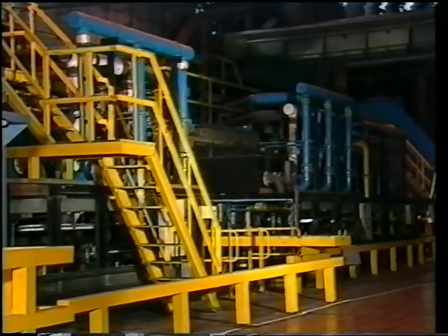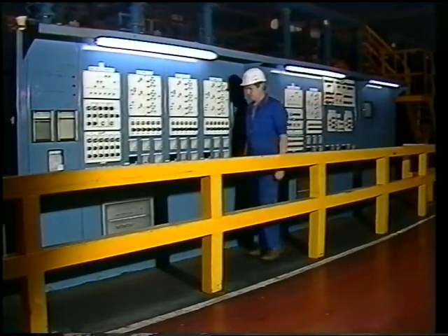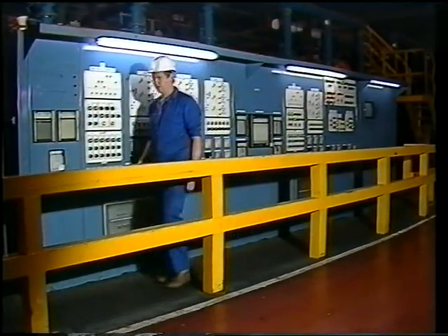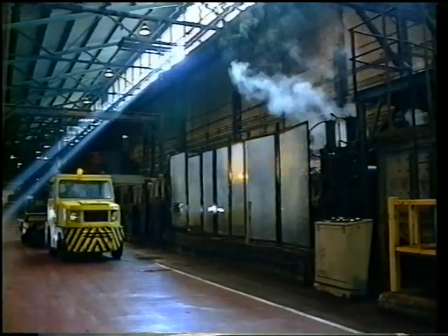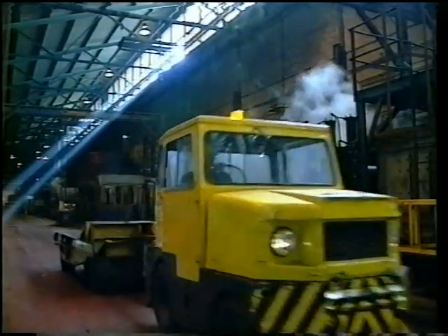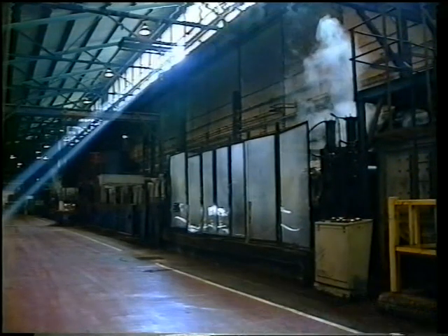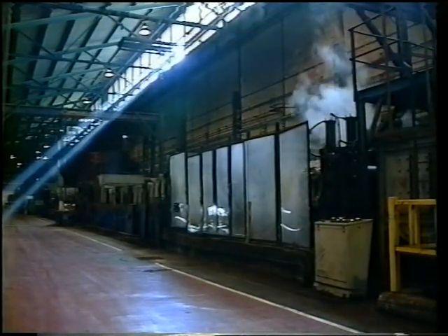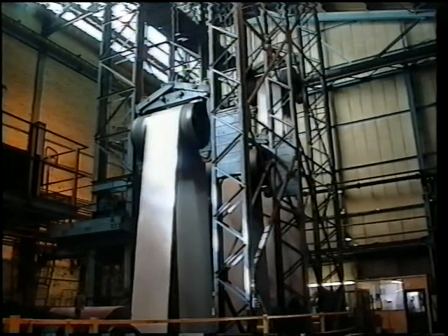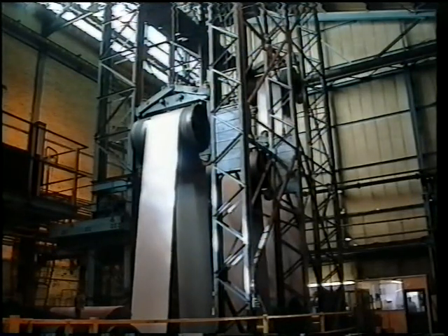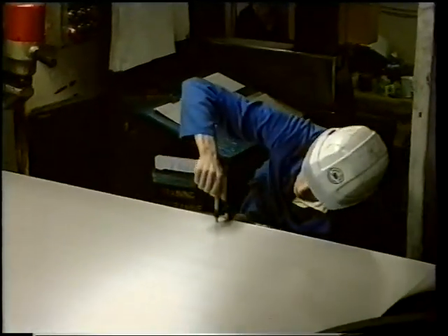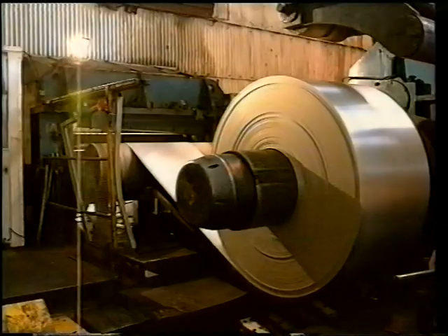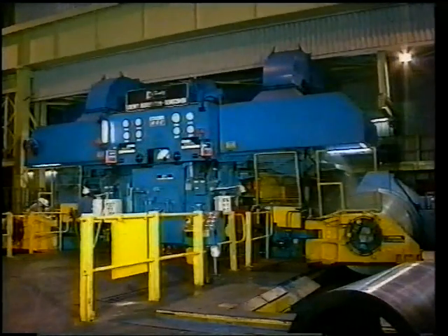The strip passes through 2 natural gas-fired furnaces and a cooling section before being shot blasted to loosen and remove the scale. The coil is then pickled in a mixture of hydrofluoric and nitric acid before being washed and dried. A further accumulator allows the individual coils to be sheared and recoiled after a final inspection. The coil is now clean and ready for rolling to the required gauge and finish in the cold rolling mills.